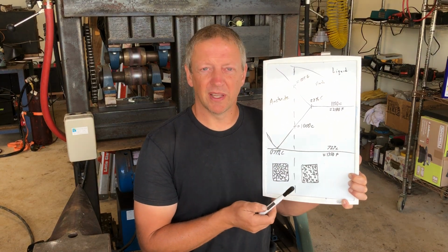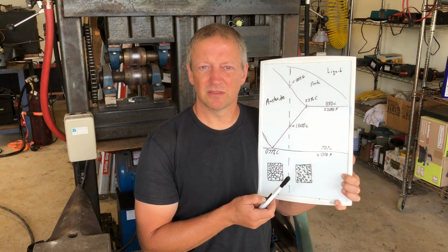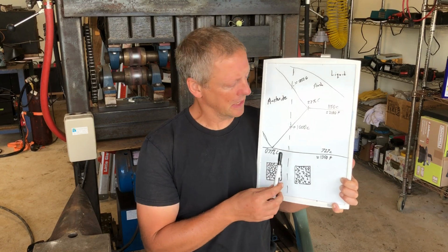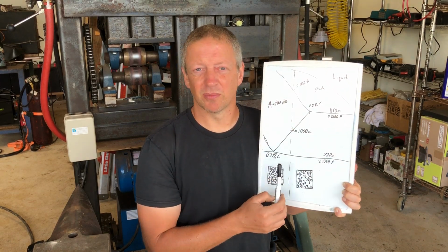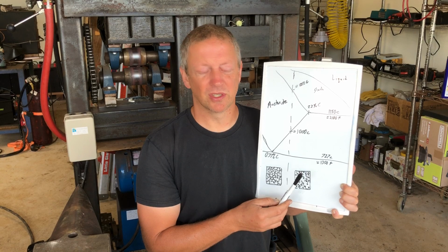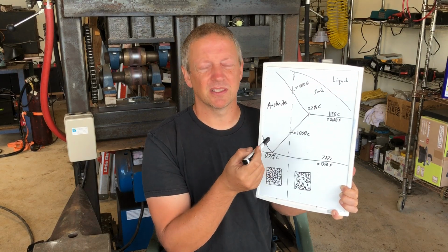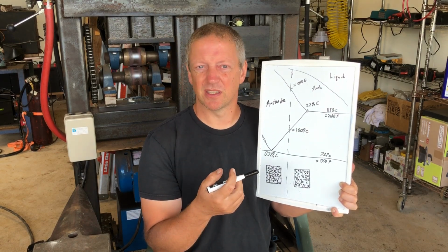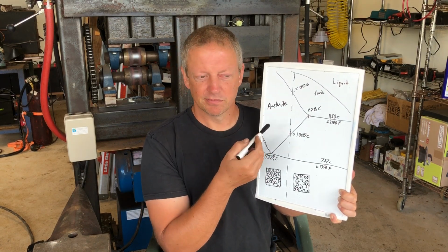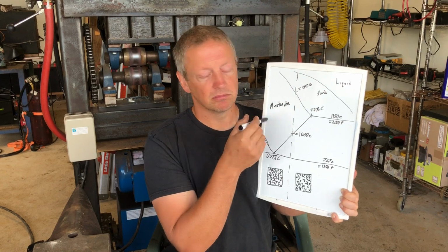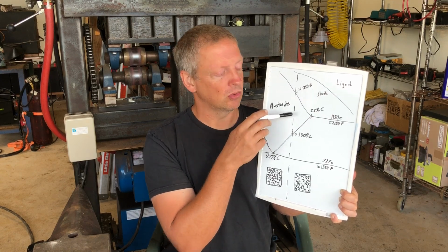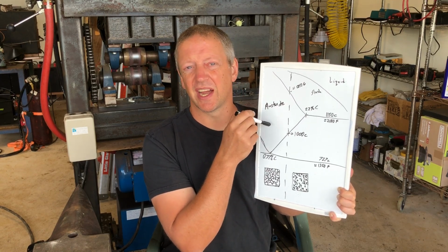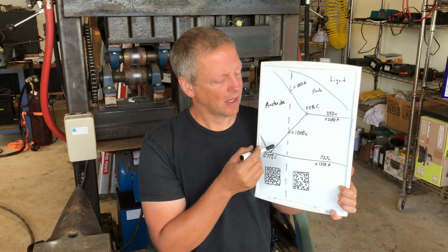So again, this is where we get into some of that pick your own adventure type stuff. Looking at this, you can see there are some choices about where to forge. The easiest forging is going to be of pure austenite. Having carbides in there stiffens the material. Things move more slowly. Depending on how you're forging or your end goal, you may decide to forge entirely as austenite.